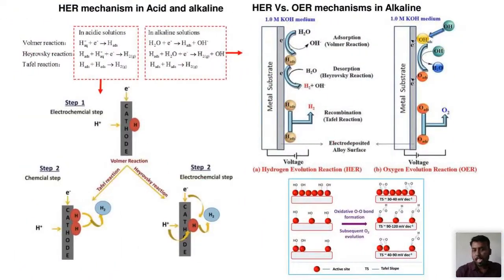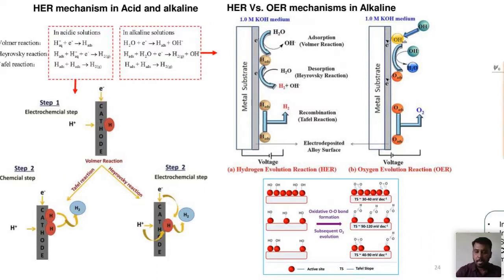And hydrogen evolution reaction mechanism and oxygen evolution reaction mechanism. So whoever is working on oxygen electrocatalysis and hydrogen electrocatalysis, please pay attention to this mechanism. For instance, in the case of hydrogen evolution, 3 types of steps are very important mechanistic pathways. That is Volmer reaction, Heyrovsky reaction, and Tafel reaction. These are very important reactions. In the case of HER and OER in alkaline condition, adsorption, desorption, and recombination processes are playing a major role. And the O-O bond formation is playing a major role in the oxygen evolution reaction mechanism.